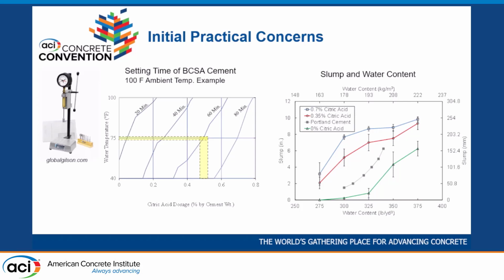And if we continue adding citric acid, the slump increases even more. So this is kind of useful just for determining initial mix design parameters, getting the slumps that we require, and the setting time that we need.